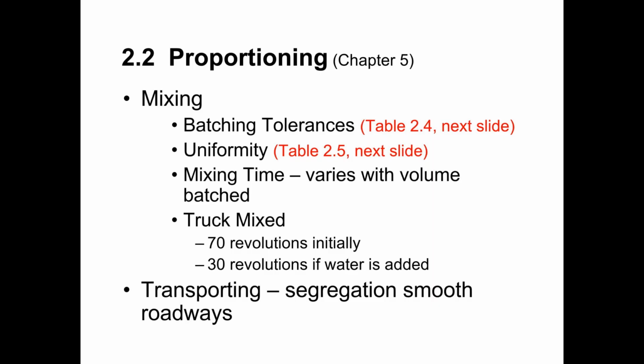Notice that generally for truck mixed concrete, it should be mixed at 70 to 100 drum revolutions at the manufacturer's recommended mixing speed in order to say that that concrete has been fully mixed. After the concrete has been fully mixed, if we make any adjustments to the concrete mix, such as adding some admixture, or adding some water if we've held out a little bit of water during the initial batching so that we have the opportunity to add a little bit of water back, then anytime we make an adjustment to the mix after it's been initially mixed, we need to remix the concrete a minimum of 30 drum revolutions at the manufacturer's recommended mixing speed.